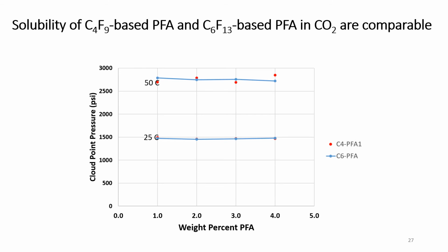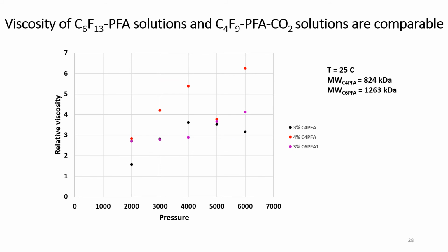Our initial tests on the C4F9-based PFAs were promising. Their solubilities in CO2 were comparable to that of the C6F13 polymers. We also found that the viscosity effects on CO2 were similar for the C6 and C4 polymers, making C4F9 PFAs a promising alternative to C6F13s as well.